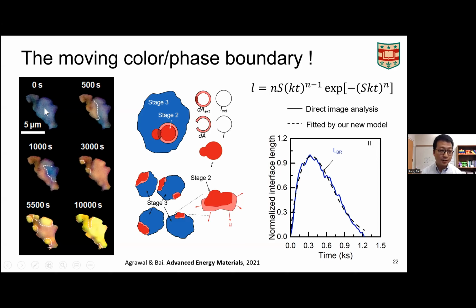Initially, we don't have a phase boundary, we don't have a color boundary, and then we have a length over here, the length changes, and the length vanishes. And eventually, when another color comes up, it shows up again, and it eventually vanishes again. So using this simple, well, probably not so simple equation, because we have the exponential term over here, we were able to fit the experimental discovery very, very well. And that tells us what the true physics is during this process.